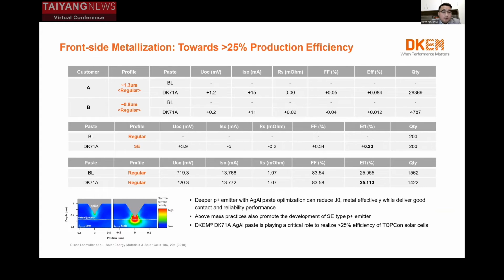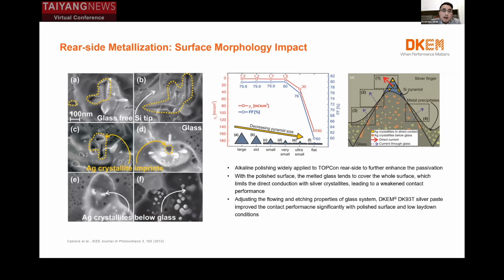The second thing is that with SE type of emitter, our DK71A AgAl paste right now can deliver more than 0.2% efficiency. With optimization of our paste and process, I think 0.3 is possible. And already our paste can work with customers to achieve more than 25% solar cell efficiency in mass production. This is our effort on the front side. Rear side is also quite important for TOPCon solar cells. So in the next two pages, we will talk about rear side metallization.